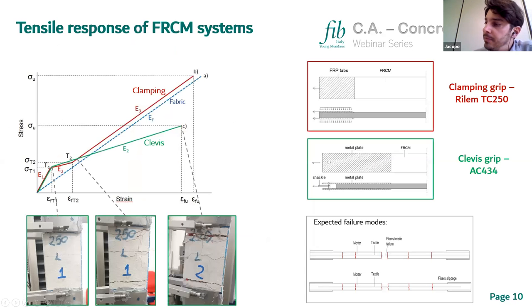So depending on the test setup, we also have different results in the tensile behavior of the material. Here I show you the different stress-strain curves by adopting clevis anchorage. In this case, we have a first part of the curve where the specimen is still uncracked. Then we have the formation of the first crack and then the formation of further cracks. In this case, the slope of the curve is lower.